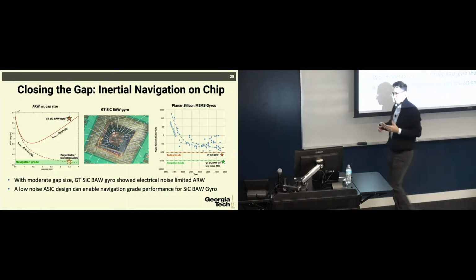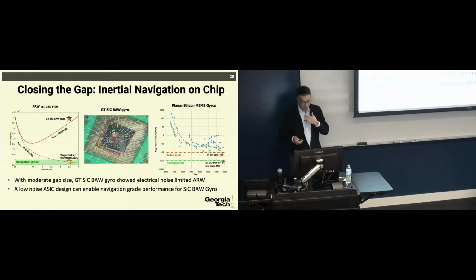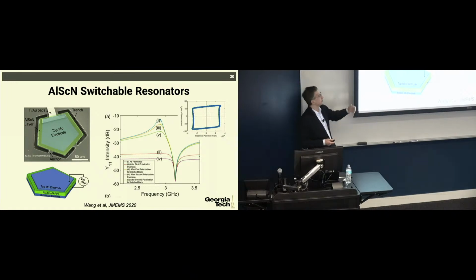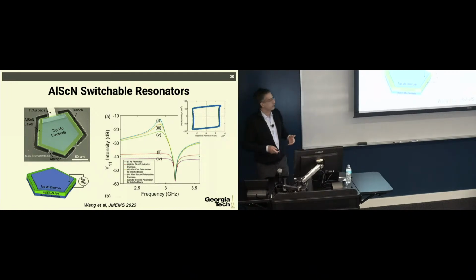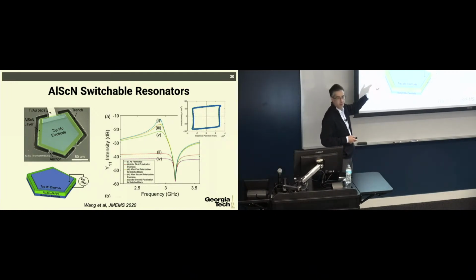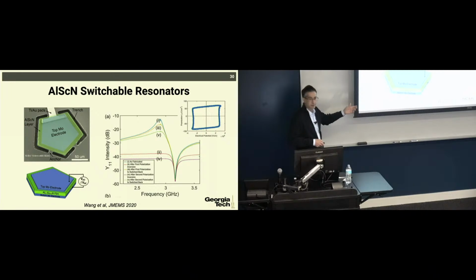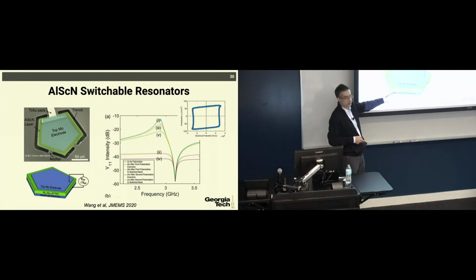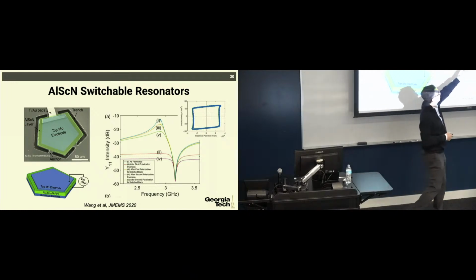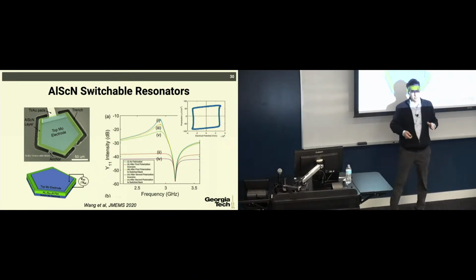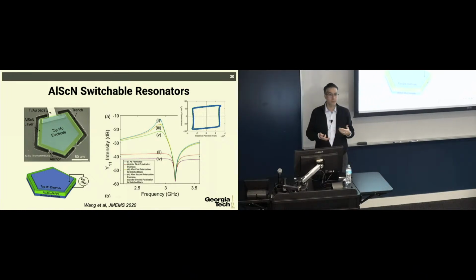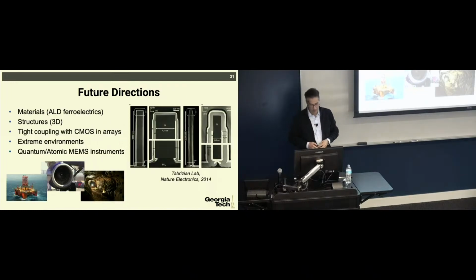So MEMS is going to flourish for years to come, I think not just through silicon carbide, but through a variety of other materials for other types of applications. For example, aluminum nitride turns out that if you dope it with scandium, you can get a much higher piezoelectric coefficient and much better performance compared to just pure aluminum nitride. On top of it, it becomes a ferroelectric material, so you can use the ferroelectricity to turn the resonator on and off by application of a DC voltage. So you don't need any switches to be integrated with these devices. You can just apply a DC voltage to turn them on and off.